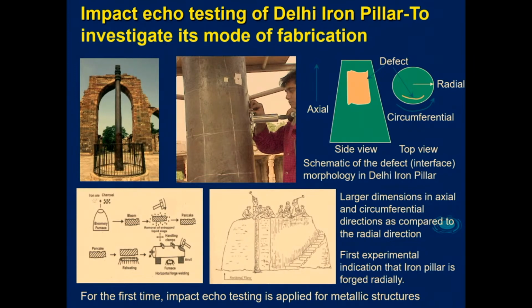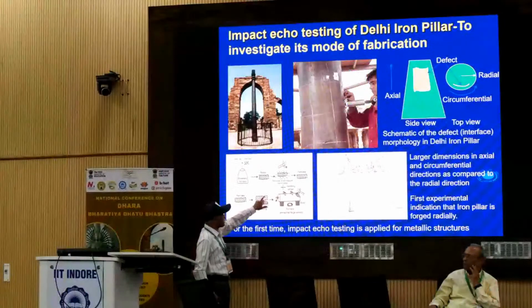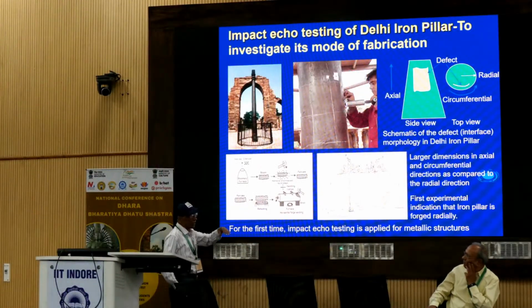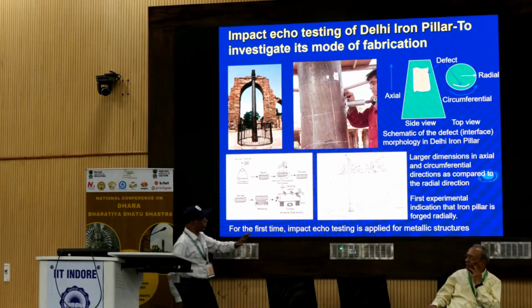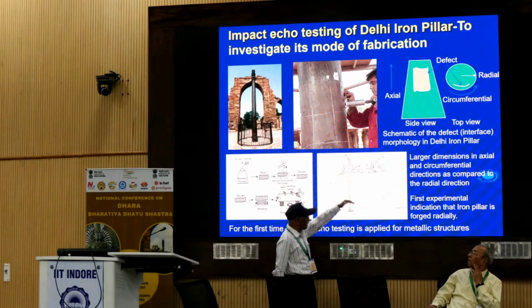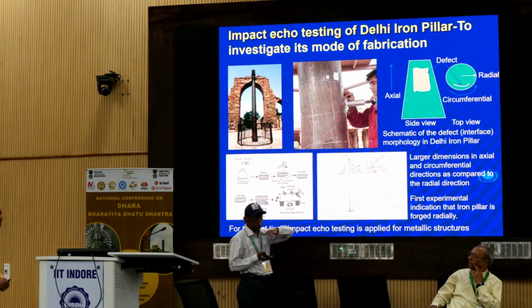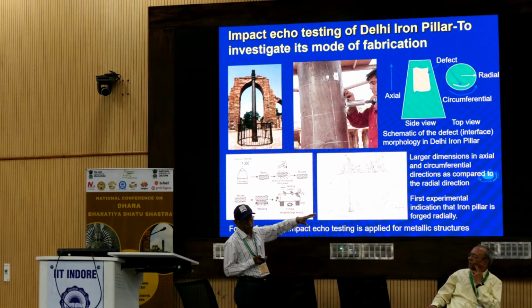That is essentially because when you do the hammering in the horizontal fashion, you will see the interfaces in the circumferential axial orientation. Whereas if you do the pillar in this fashion, all the interfaces between the lumps would be in the radial circumferential direction.